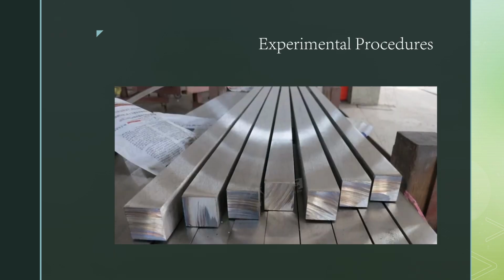How about 28 samples with dimensions of 0.5 inch by 1 inch by 0.3 inch, with 7 samples at each temperature. The aging temperatures will be 20 degrees Celsius, 170 degrees Celsius, 190 degrees Celsius, and 240 degrees Celsius. But first, samples are fully solution annealed for 1 hour at 495 degrees Celsius. Can't forget that. What are the holding times?